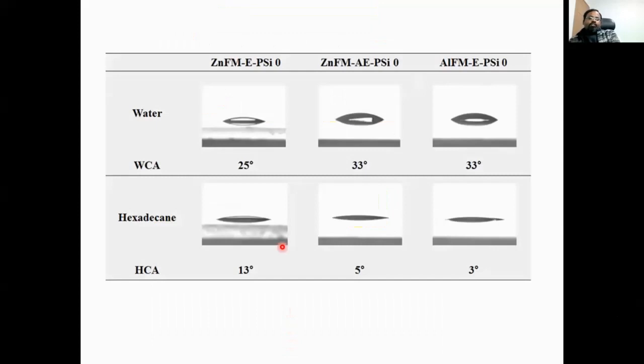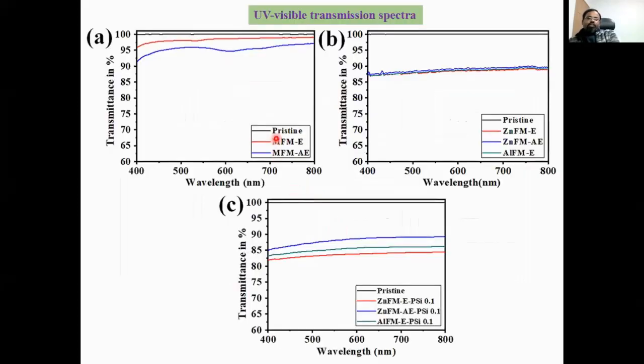So we also checked in the absence of silica, where we used only polycaprolactone triol to make this coating, which also shows good hydrophilic properties, and maybe oleophilic property, because it's suitable to oil. So this amphiphilic behavior is very good. And further, we tested the transparency of our coated substrate. Without reacting with metal, it shows very good transparency because the solution is highly transparent and stable. So the coated substrate also shows very good transparency. Whereas after reacting with metal, because the solution looks opaque, the transparency is partially reduced, but it's quite okay to use these coatings for applications.